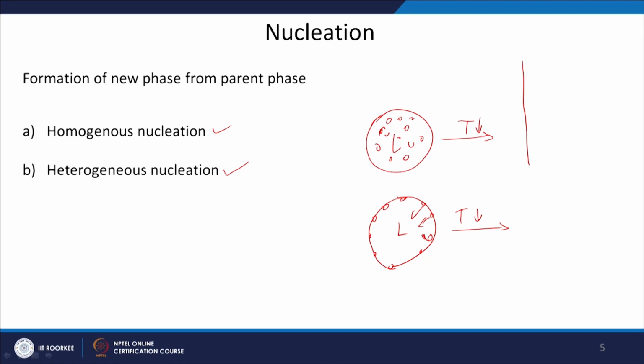And what actually decides this whole process? You will see that, in general, heterogeneous nucleation is the one which is going to be dominating. To achieve homogeneous nucleation, you have to have very specific conditions. In fact, it is a very difficult process, to have homogeneous nucleation, and the reason is this. Suppose, let us say, I draw a free energy curve here.